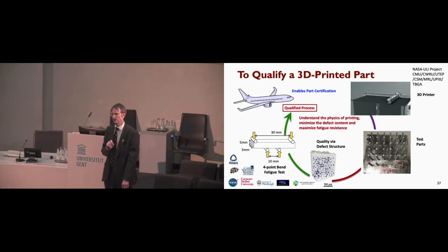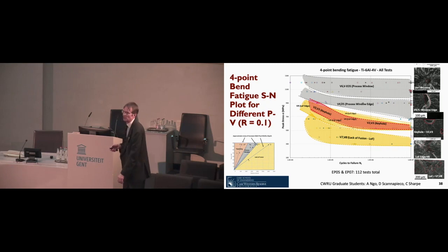If you're wondering why four-point bend fatigue, it's actually a pretty efficient approach to this problem. And the idea is to connect all the way from the printing through this crucial mechanical behavior to show that this process window approach is equally valid in terms of mechanical behavior. I suspect it will work out also for corrosion. And just to lend some verisimilitude, if you like, to my assertions, this somewhat confusing slide, I admit, is examples of SN results from the four-point bend fatigue, and the different colors correspond to different places in the process window.